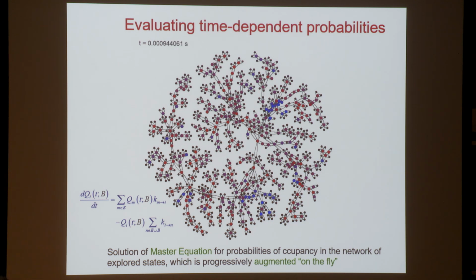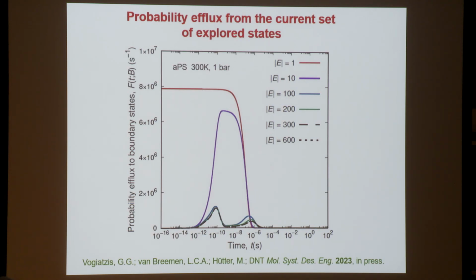Having done this solution of the master equation, one can look at some features of the temporal distribution. One thing that one can look at is the probability efflux into the boundary states as a function of time. I show you this for different sizes of the set of explored states: initially just one state, then 10, 100, 200, 300, 600, etc. Remarkably, one observes that if the set of states is large enough, this efflux of probability into the boundary states as a function of time stabilizes at a certain shape, characterized by the presence of well-characterized maxima. For example, this is polystyrene at room temperature. There is a maximum at 10 to the minus 10 seconds, and another one at 10 to the minus 6 seconds.